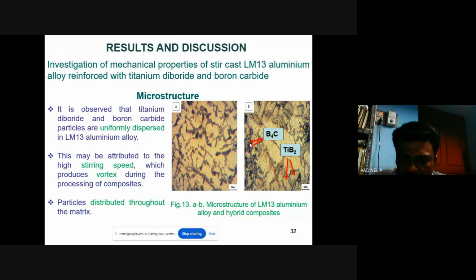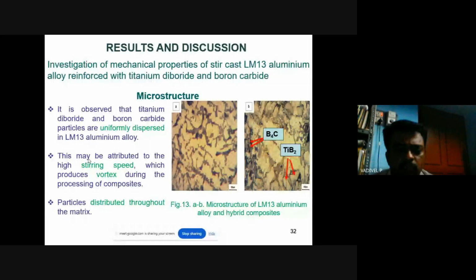See, these are the particles shown in the red mark, that is titanium diboride and boron carbide. This is attributed to the high stirring speed which produces a vortex during the process of making the composites. The particles are distributed throughout the material.